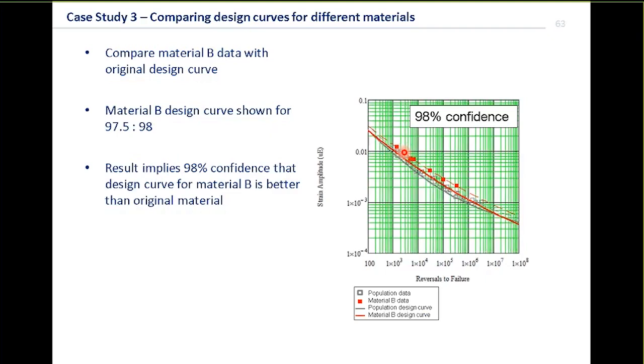So in this case, we do accept that they're different, but we can do an analysis, and this analysis actually shows that we have a 98% confidence that the new material is better than the original material, even though we've used just a limited number of samples for that. So using this sort of approach enables us to go and explore lots of materials and prioritize those. Other areas where we do a lot of this is in things like motorsport, where they're looking for new materials to replace old ones to get ahead of their competitors. And so what we're looking at is comparing different recipes of materials to see how the fatigue behavior compares, so that we can shortlist materials which can be used for later production and research.